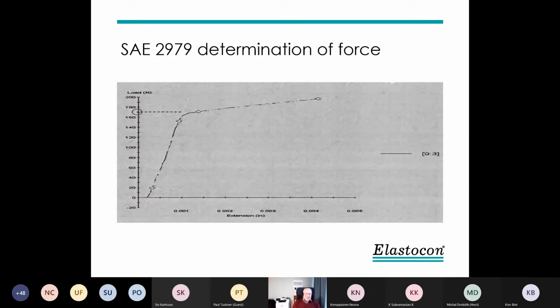Here is a graph from the SAE standard, where this intermittent test is described with a test jig similar to the one we saw before. And the way of determining the force is that you measure the force while you make a further compression. And when the rubber sample doesn't have any connection or touch the spacers anymore, you get another curve, and you then take the value as indicated here. The first steep part of the curve is the metal, the deformation you are measuring, and then it's the rubber deformation. And it can be done if you have a tensile test with a good measuring system.